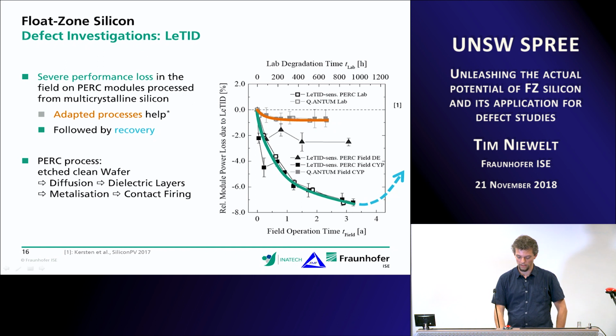consists of these steps. So we start with an etched clean silicon wafer. Then we apply a diffusion to that, add some dielectric layers on top and on the bottom to passivate. Then we have a metallization so that we can get current out of it. And then we do contact firing, and it's a PERC cell.